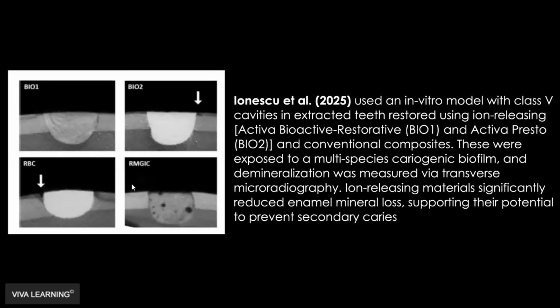In the pictures, you can see in the regular resin-based composite, right next to the filling, those radiolucencies. Those are areas where mineral loss has occurred next to a regular filling material. Where you look at RMGIs and the Activa materials, particularly the original Bioactiva, next to it you don't see any dark areas. Around Activa Presto, which was like their light cure only version of the material, I guess it showed a little bit of demineralization, but not as bad as a traditional composite. So that is the one evidence that it prevents demineralization.